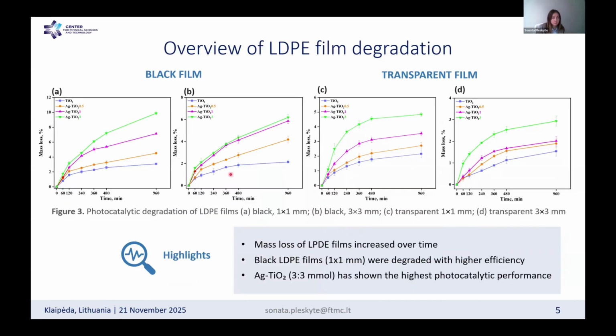So in general, the degradation efficiency, the mass loss of LDPE films, increased over time, and you can see that the highest degradation efficiency was obtained for black colored LDPE films with a size of 1 by 1 millimeter over here, and it reached almost 10% of mass loss. And also I want to add that the highest degradation efficiency was obtained with silver titanium dioxide nanomaterials which contain the highest concentration of silver.